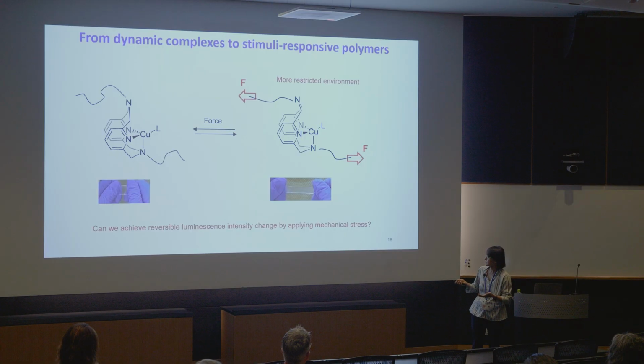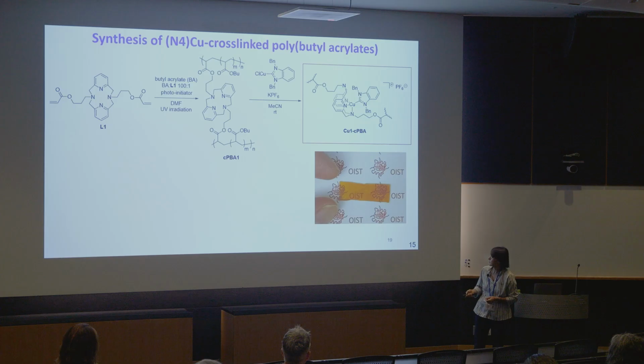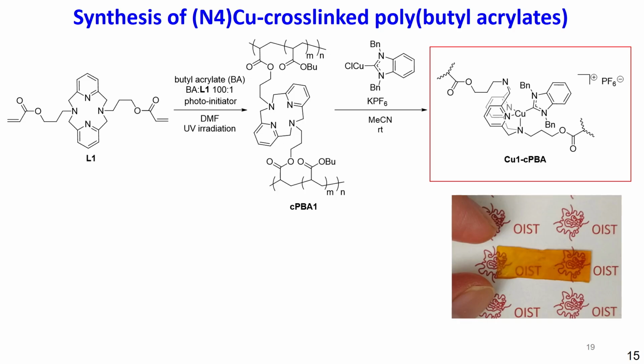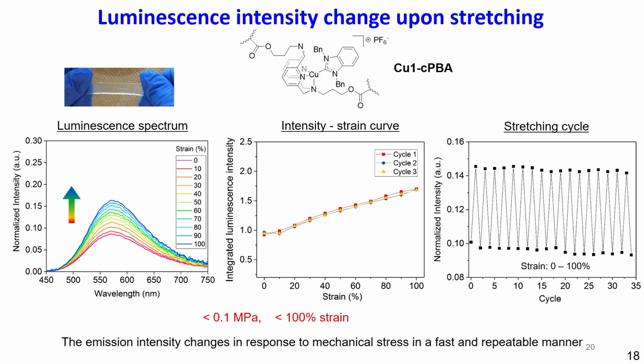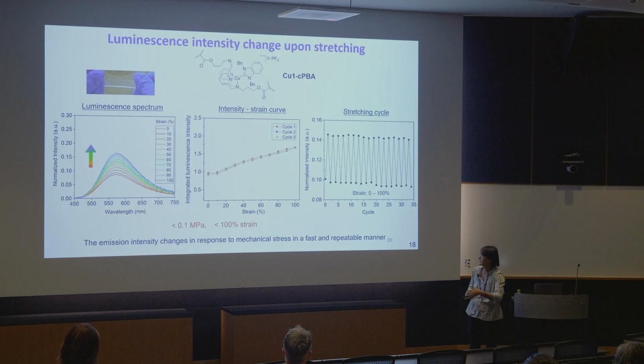So the next step was we attach it to the polymer and try to stretch it. And this is how we make it. I will not talk too much about this. The films are essentially photoluminescent, and that's all we need to know for now. So what we do next, we stretch the films in the tensile stretching machine, and we record the photoluminescence intensity. So we see as we stretch it, so this is the degree of stretching, this is an increase in the photoluminescence intensity. But also as we release it, it decreases again. And this can be repeated through multiple cycles.